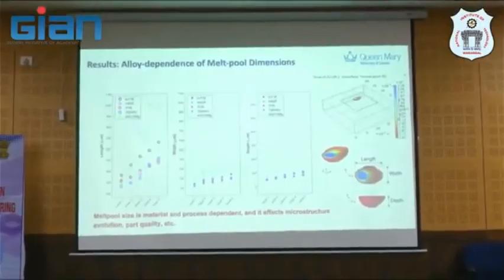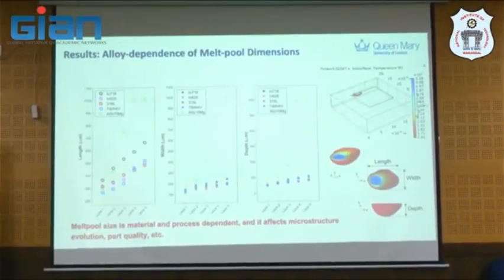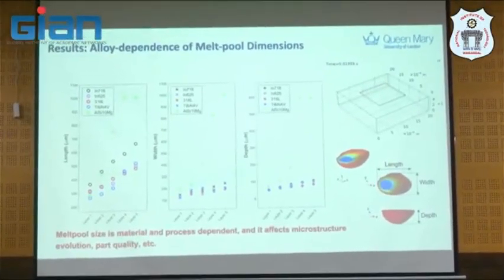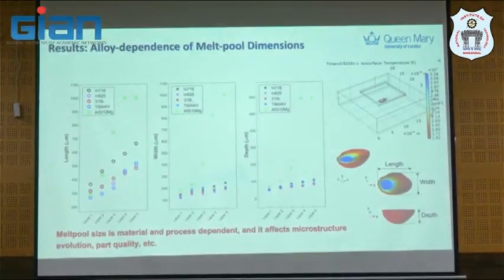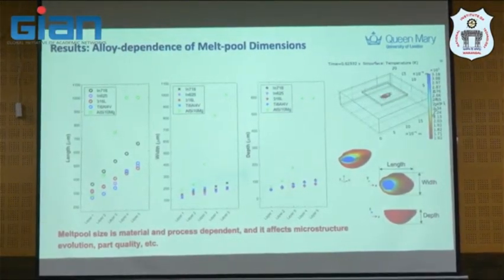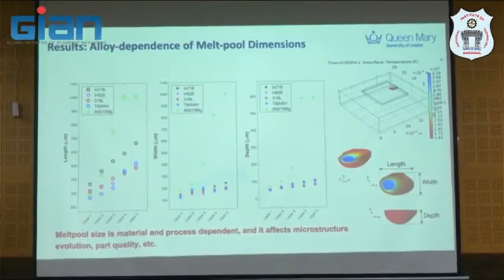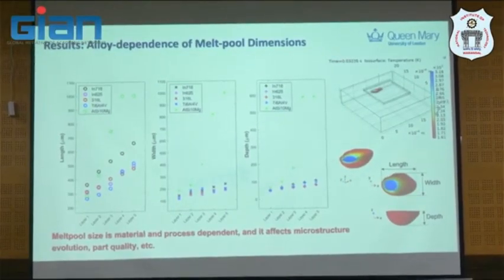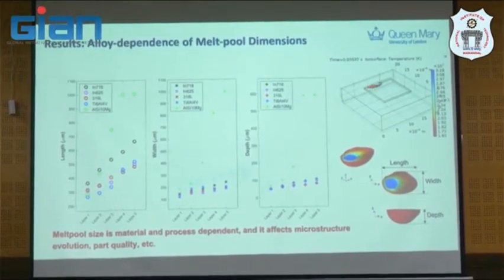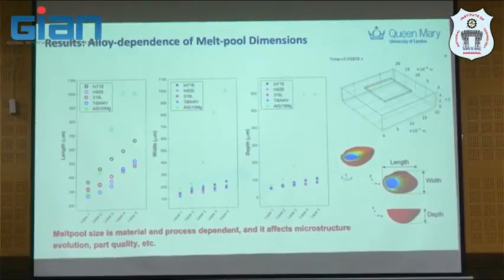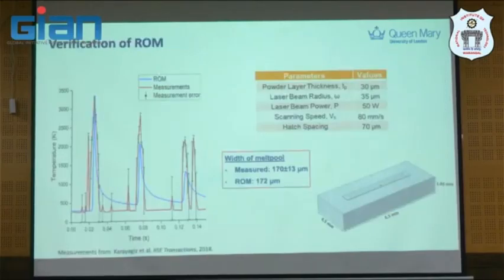You will see it's a bit different, apart from aluminum, which is behaving so differently from the others. And then you can characterize and get some features that CFD people are trying to predict. So this melt pool size is material and process dependent, and it affects the microstructure evolution and part quality, that we all know. And this has been validated against the available data at the condition investigated here.